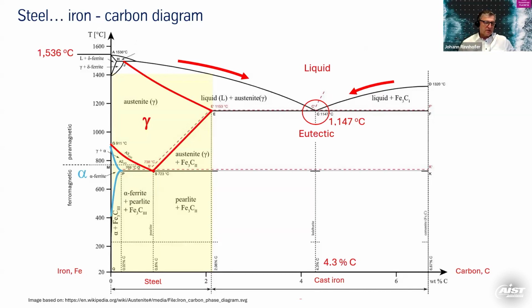We have more than 3,500 types of steel for that reason, because we have so many options to alloy steel with carbon and also other alloys like chromium, nickel, and other metals, and also heat treat them in different modes, so to say. A very interesting feature is the different crystal shapes which we can have. This is the austenite at high temperatures and the ferrite at low temperatures, and all sorts of combinations in the end. What we will also need later is a special feature of steel, which is the magnetic properties of the steel. So below the Curie temperature, which is around 770 degrees C, steel is ferromagnetic and it is non-magnetic beyond that temperature. So that is very important for induction heating.